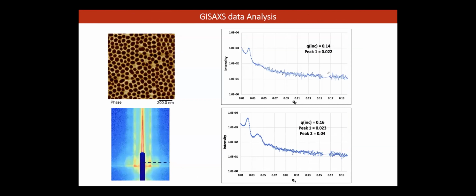So normally you would do a couple of different angles. You do angles of incidence, grazing angle of incidence below the critical angle of the film, which for us is about something like 0.12, not shown here, but then you do at the critical angle and you do higher than the critical angle. So you probe. The higher the angle, the deeper you probe into the film. So at the critical angle, you're just grazing the surface. And you can get different information. So for this membrane structure, for example, at 0.14 degrees, you see only one peak, okay?